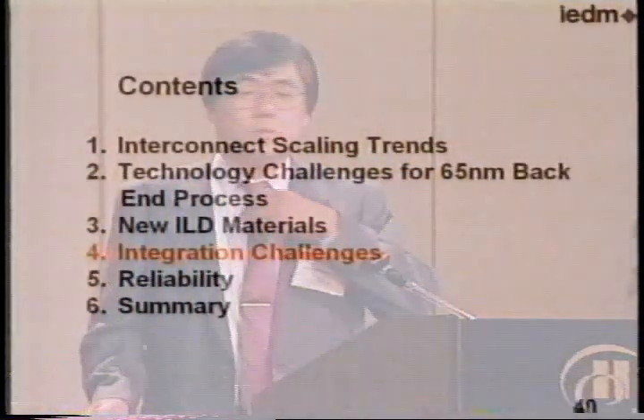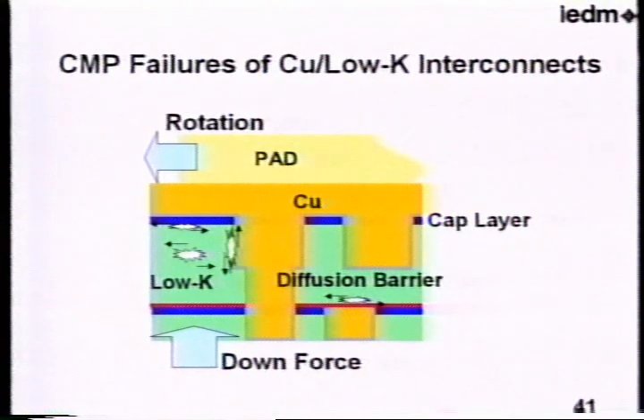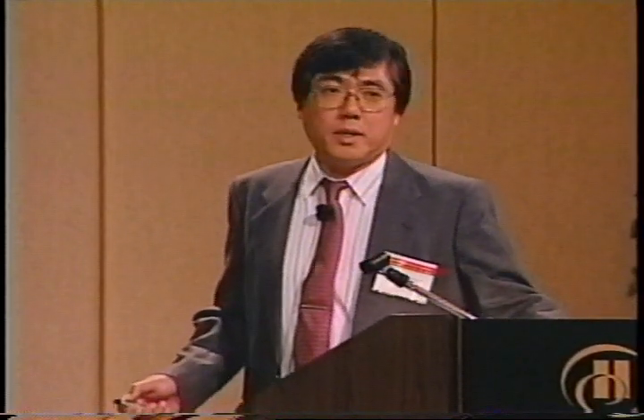Next, I'll move to our integration challenges. This picture shows possible CMP failures of copper low-K interconnect. There are metal delamination or cracks during CMP with a mechanical friction. To prevent this kind of delamination or crack in the film, we should develop a new slurry and also a new pad, and also reduce the downforce process is important.